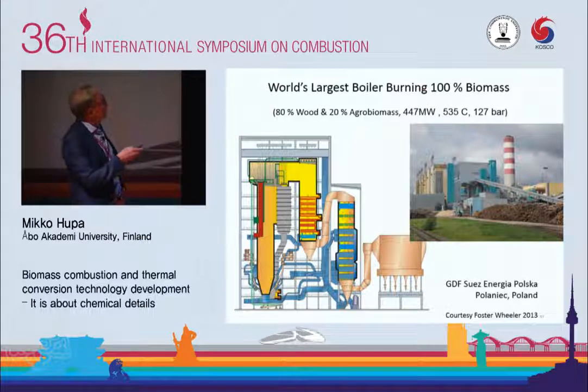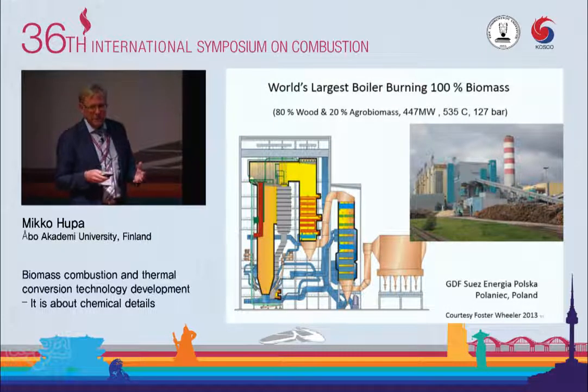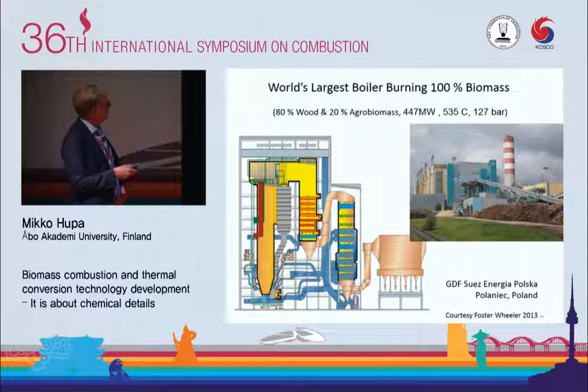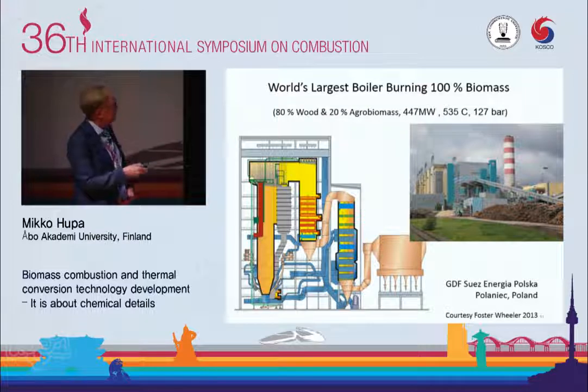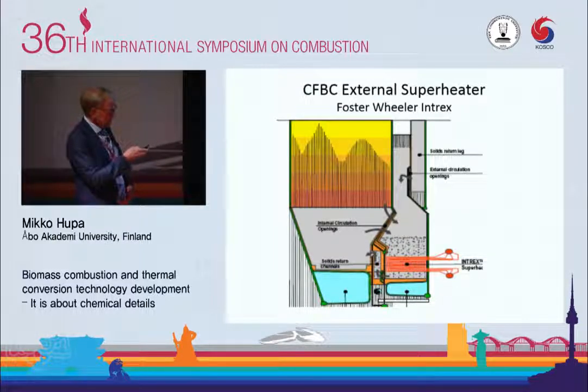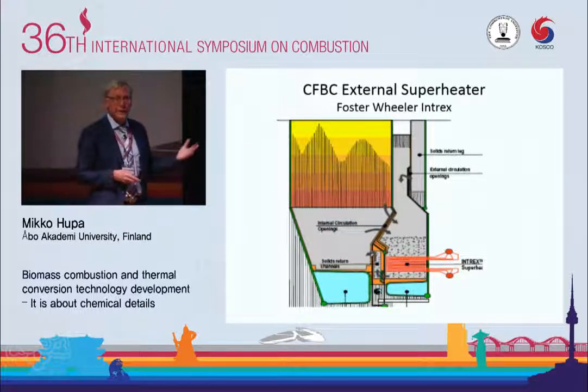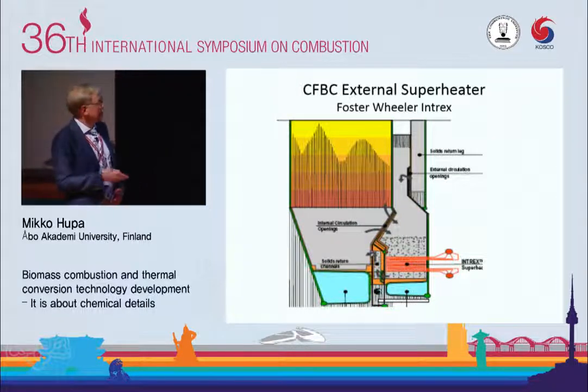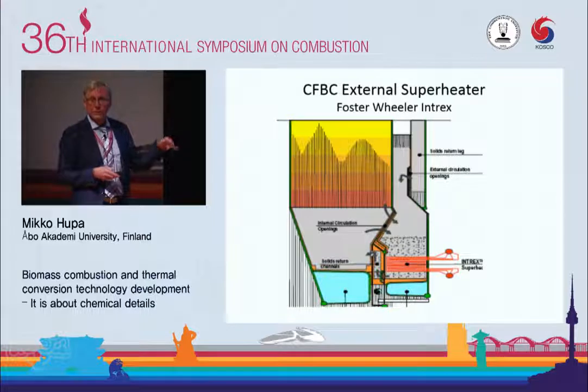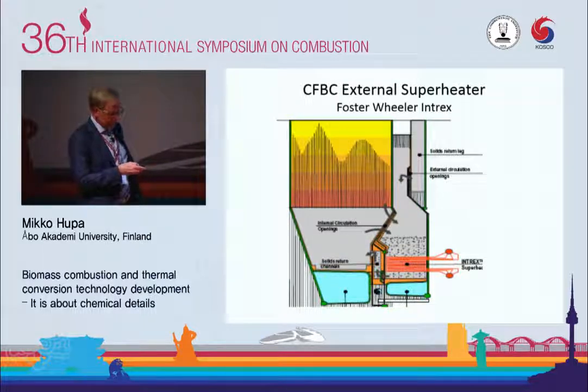And how do they do this? Because they also use agrobiomass, which is the more difficult one, containing chloride. One solution they have, which is interesting, this is Foster Wheeler in Poland. In a circulating fluidized bed, this is the furnace. The bed material is circulated back, and there is a feeding system of that back to the furnace. That feeding system is also a small bubbling fluidized bed, and they put a heat exchanger, the hottest superheater, in there, and could increase the steam temperature somewhat by the contact with the hot sand without the contact of the flue gases and the chloride. This is one way of showing how things advanced anyway.